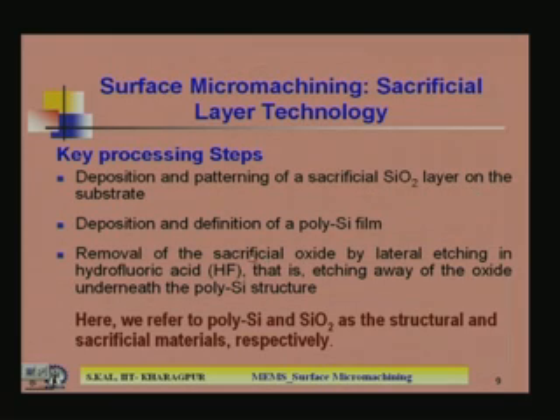Next step is deposition and definition of a polysilicon film. If you remember the cross section diagram, you can see that after the sacrificial patterning we are depositing the polysilicon film. Then removal of the sacrificial oxide by lateral etching in hydrofluoric acid. Hydrofluoric acid is a choice if you do it on an insulating layer. If you go for etching of silicon dioxide on silicon nitride, then there is no problem with hydrofluoric acid.